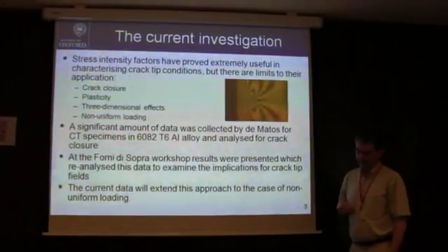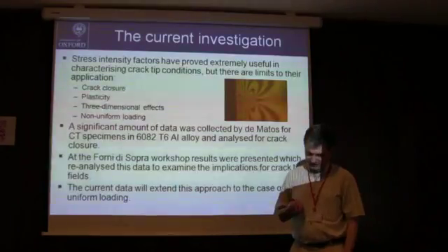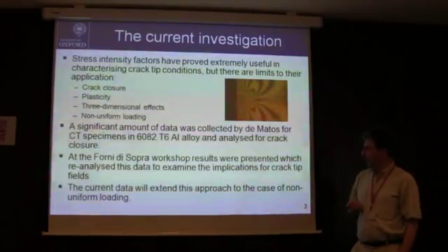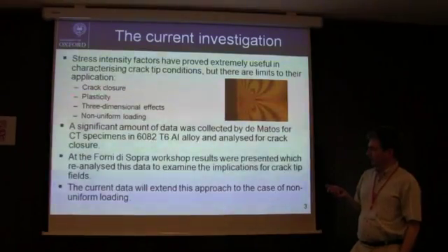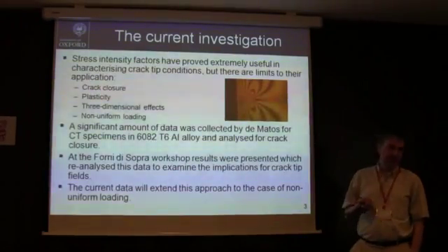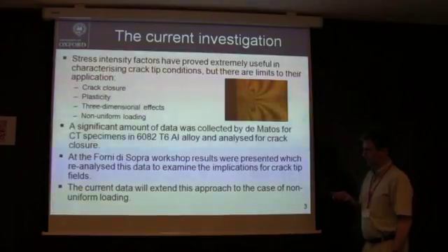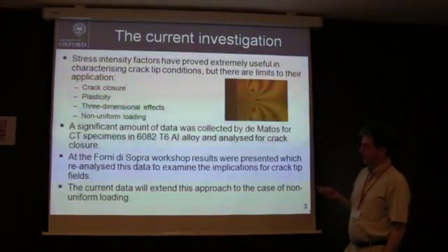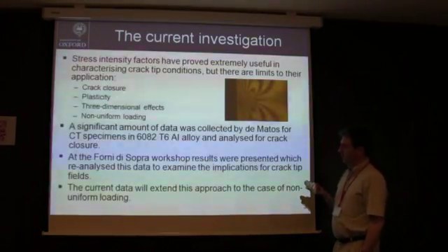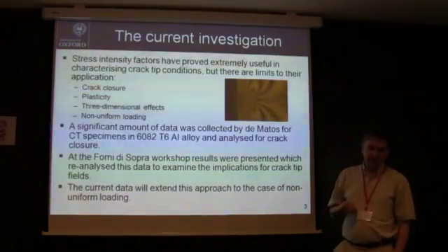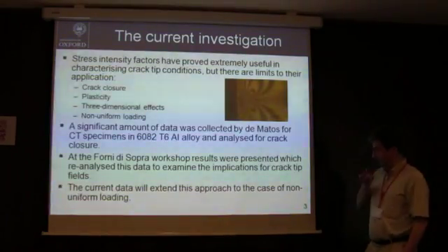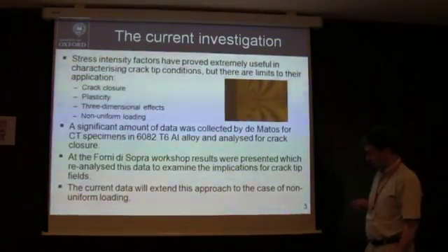But the stress intensity factor is based on an elastic analysis of the structure, and it doesn't in particular account for things like crack closure, whether roughness induced or plasticity induced. It doesn't account directly for plasticity. There are often three-dimensional effects which can be quite important, and as we've said, there can be non-uniform loading.